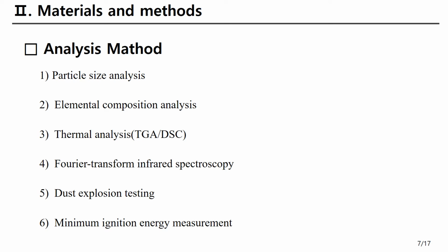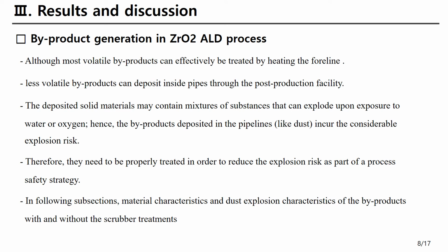This is the analysis method. And the byproduct generation in zirconium oxide ALD process, although most volatile byproduct can effectively be treated by heating the foreline, less volatile byproduct can deposit inside pipes through the post-production facility. The deposited solid materials may contain mixture of substance that can explode upon exposure to water or oxygen. Hence, the byproducts deposited in the pipeline incur the considerable explosion risk. Therefore, they need to be properly treated in order to reduce the explosion risk as part of a process safety strategy. In following subsections, materials characteristics and dust explosion characteristics of the byproducts with and without the scrubber treatment.